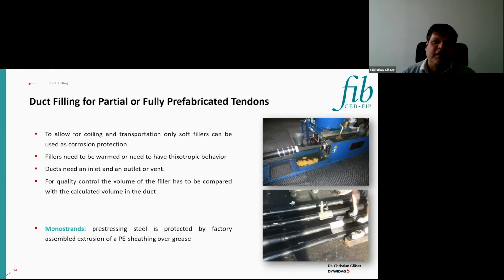Starting with partially or fully prefabricated tendons. For these types of tendons, only soft fillers can be used, because otherwise coiling will not be possible. So the fillers are typically fillers that need to be warmed up or have a thixotropic behavior. All the ducts have inlets and outlets or vents to allow a proper filling of the duct. And during the duct filling, of course, a quality control needs to take place.